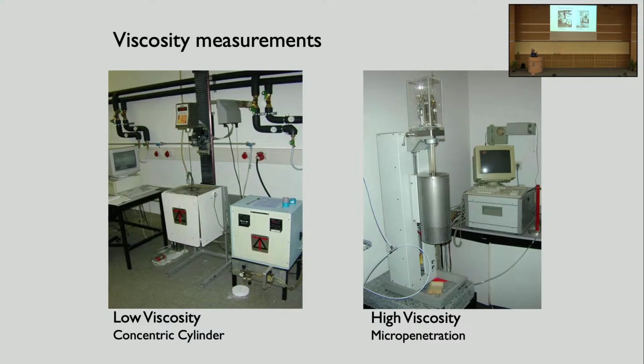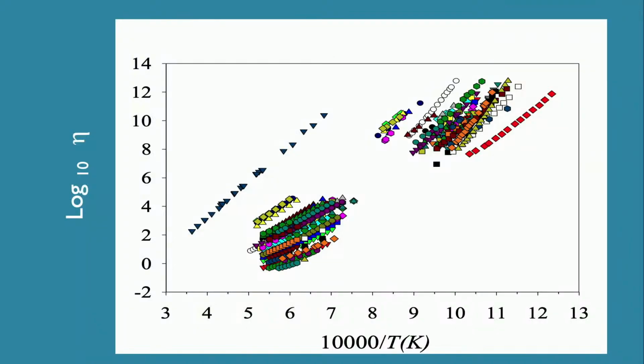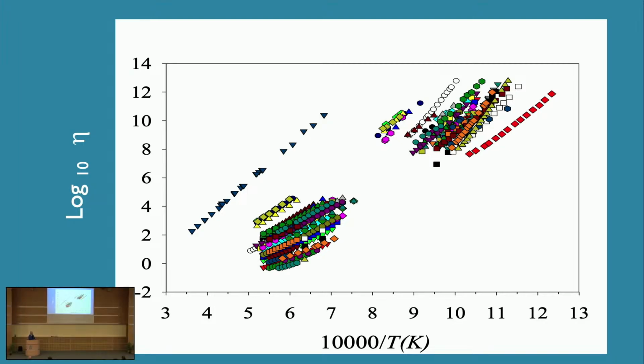So we have high temperature viscometry using concentric cylinder technique. You probably did this experiment in high school. We have micropenetration dilatometry, which allows us to deform very highly viscous materials. And by looking at the viscosity over this very wide range of its value, we can get a global curve for the temperature dependence of the viscosity of the liquids. And you can see that when we try to plot it versus an Arrhenian temperature, very few liquids, in this case just one example, show a value of Arrhenian viscosity temperature dependence, and all of the other samples misbehave. They're horribly curved. They do not express an Arrhenian temperature dependence.